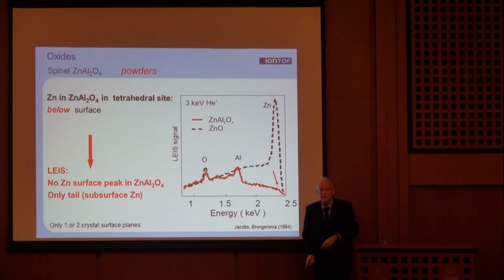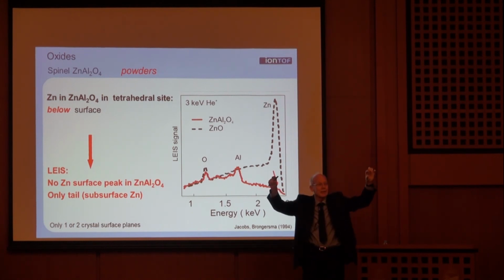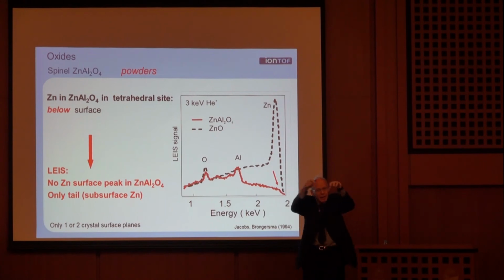What does that tell me? Well, if I have real zinc oxide, yes, I can see the zinc. But the zinc is not in the top layer, because then there would be a peak. It is just below. In zinc aluminate, the zinc atoms are half an atom down. And because of that, they cannot participate in the chemistry, and you don't see them in ion scattering. You only see them as a background.